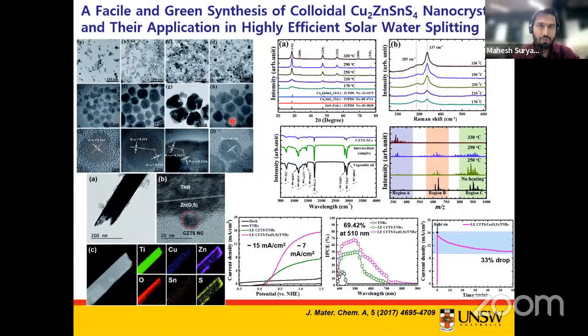Before that, I would like to tell you that the techniques such as the hot injection or the heat-up approaches that are used to produce these monodispersed nanocrystals usually contain highly toxic and flammable solvents such as oleylamine, octadecene, and oleic acid, which are organic solvents. So to avoid the use of highly toxic solvents, we came up with an idea of using vegetable oil and deep eutectic solvents as a reaction media to synthesize these copper chalcogenide compounds, such as CZTS and copper antimony sulfides, which I will discuss in my next slides.